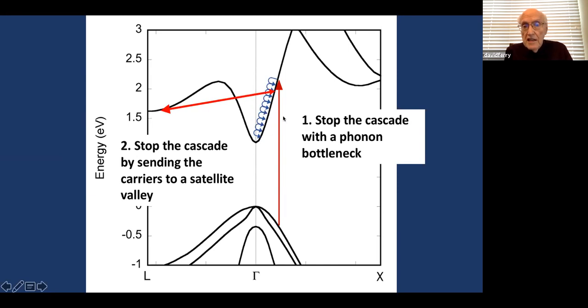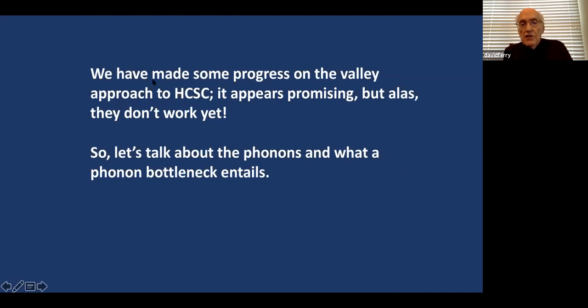And that stops this cascade because they don't need to emit so many phonons. So you're going to save about half or 2/3 of that cascade by putting the electrons over here in what we call valley photovoltaics. Put them over here and extract them from here so you achieve the second part of the Ross and Nozik as well. So we made some progress on this valley approach to hot carriers. It appears promising, but as yet, just like the Ross and Nozik, they don't work well. So we're trying to figure out what that is. And we hope to have some solutions. There's a new design that's in test now. Ian promises me we'll have data within a few weeks. I say to Ian, you're not driving your graduate students hard enough. Got to get the whip out and keep them working.